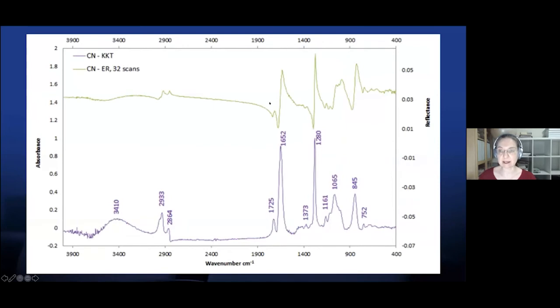Alternatively, if the external reflectance module is used, no contact is required. First of all, you would obtain this external reflectance spectrum, which doesn't really make sense. However, you can simply press a button and this performs a Kramers-Kronig transformation that changes this strange reflectance spectrum into a more familiar looking absorbance spectrum, which could then be matched against your reference database. I would recommend starting by learning how to use the ATR module and then later build up your expertise and then learn how to use the external reflectance module.